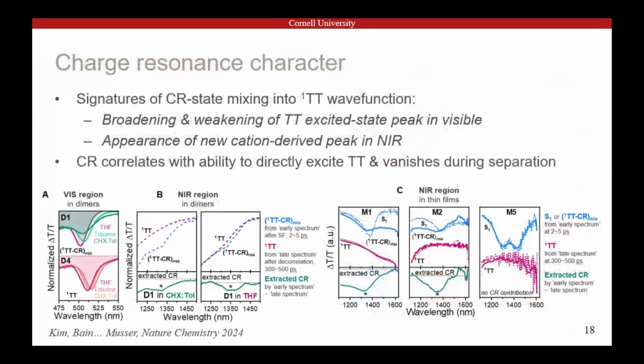We can go further and look at the information that we often throw away as spectroscopists, the details of the spectral fingerprints. Typically, once we identify this is the fingerprint of the triplet pair state, this is the singlet, that just lets us extract the dynamics of these different characters. But these excited state absorption spectra carry a wealth of information about the nature and the properties of the state we're looking at. And the key for us here is that in all of the systems that let us directly excite this pair state, the triplet pair signatures carry these unique peaks in the near infrared, or unique solvent sensitivity in the visible that tell us there's a very strong character of charge transfer states, or in fact, charge resonance states in the wave function.